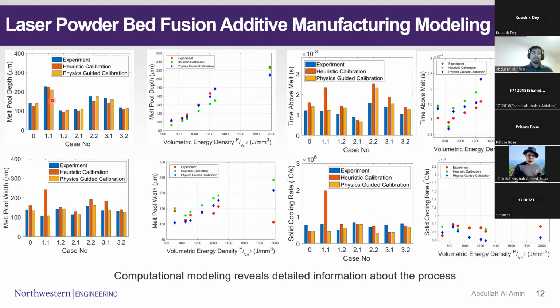The first one is the measurement of the melt pool depth. The depth is estimated from the top surface of the additively manufactured powder bed down to the level where it has, let's say, the maximum melted region. So you can think of it as the penetration of the melted region. For different process conditions, these 7 case numbers, the blue bars represent the experiment.